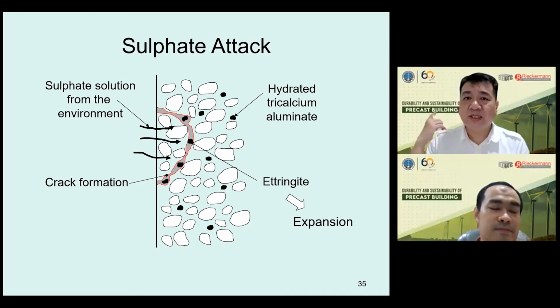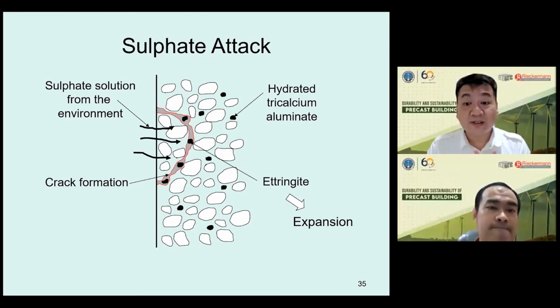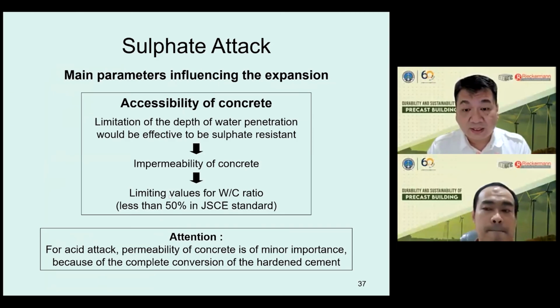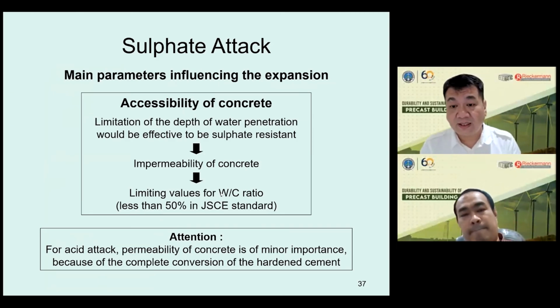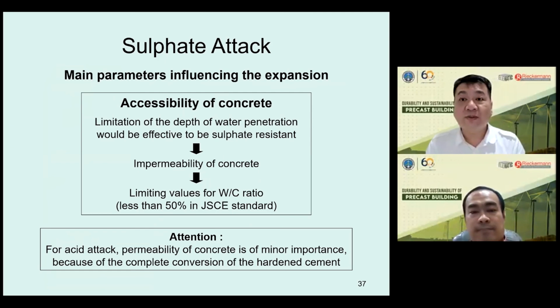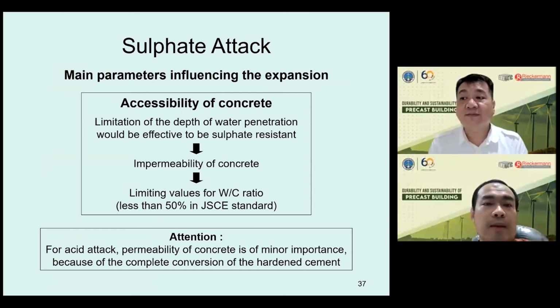It's better to use additive to reduce the water cement ratio to be lower. So this is one answer, limiting the water to cement ratio to lower than 0.5. Yeah, for the JSCE standard it is 0.5. But for now, we can make 0.4 water to cement ratio, which I think is already very good. So with fly ash or without fly ash, when we reduce the water to cement ratio, we provide better protection.